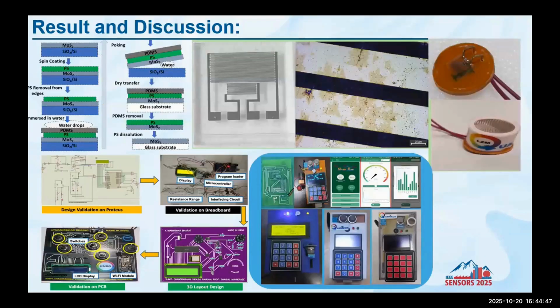After characterizing and successfully depositing the MoS2 monolayer, we did the transfer process via a surface energy assisted transfer process. Polystyrene is used as a carrier polymer to lift off the MoS2 from the deposited SiO2/Si substrate. We spin coat the polystyrene and immerse this substrate into DI water. Water penetrates between the MoS2 layer and the SiO2/Si substrate due to their hydrophobic and hydrophilic nature, and we can easily lift off with the help of polystyrene.